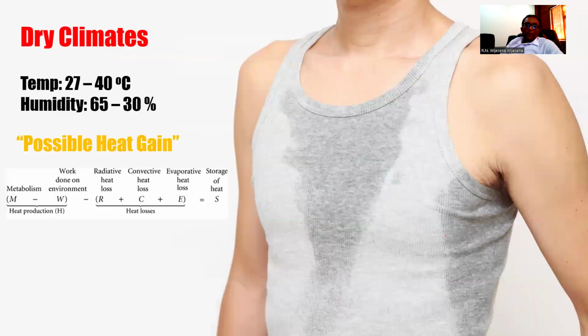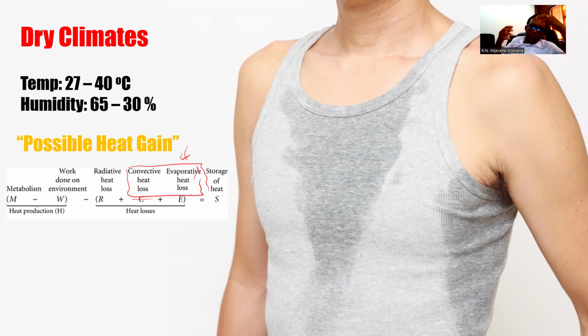And when it comes to dry climates, these areas are characterized by heat gain, because the outside environment temperature can be higher than your core body temperature, or very close. It's very easy to gain heat. If there's sun and you're wearing a cloth, there'll be a positive heat gain. So this is again characterized by high convection and evaporative heat losses. And therefore, we try to increase the evaporative heat loss. So we sometimes even reduce the amount of textile we use so that the evaporation can be more. So we have the bare skin, even higher. These are what is called very conventional strategies.